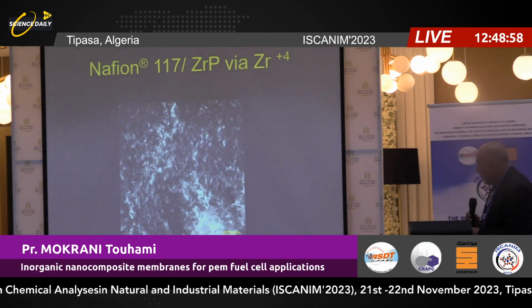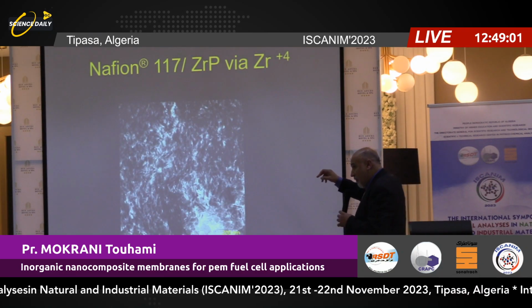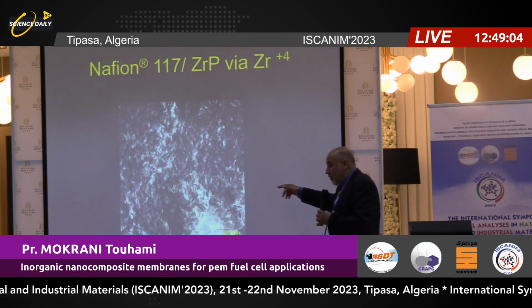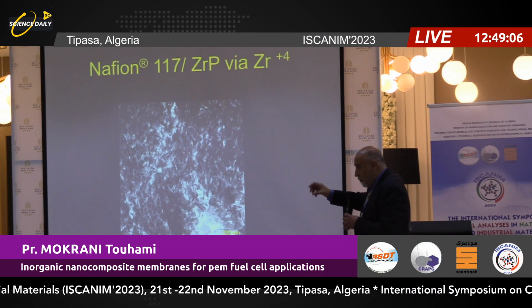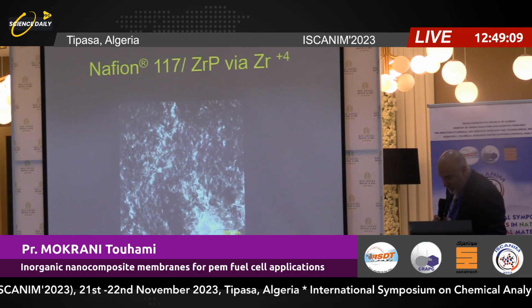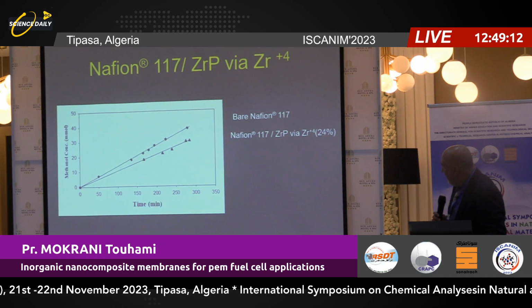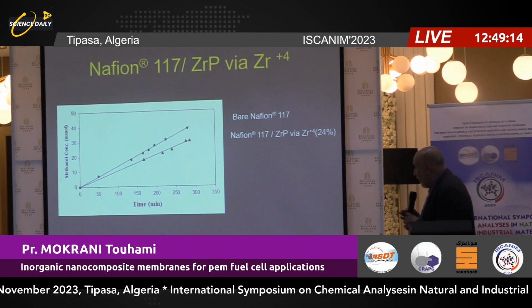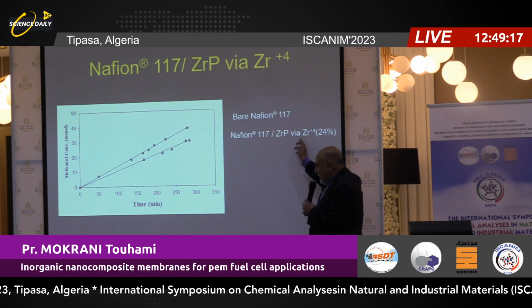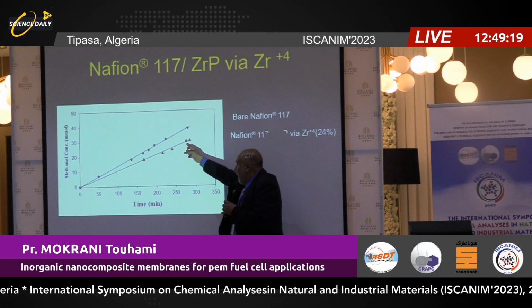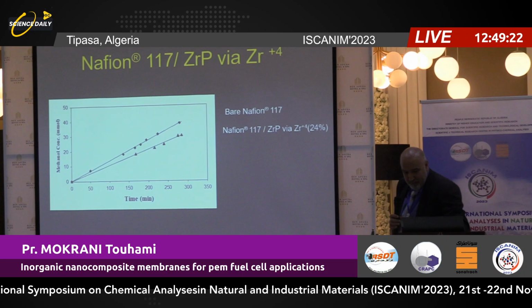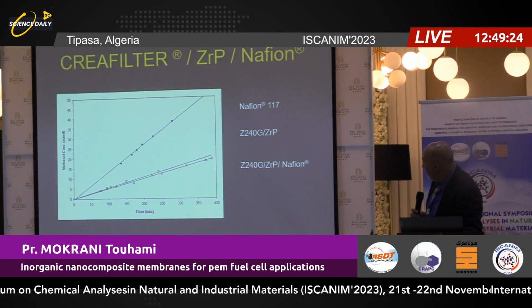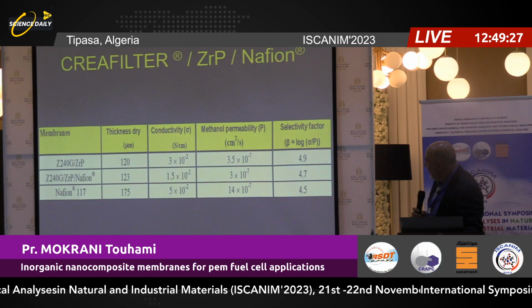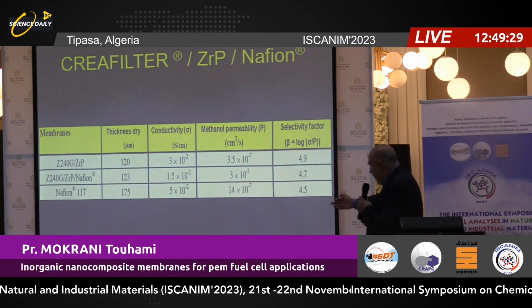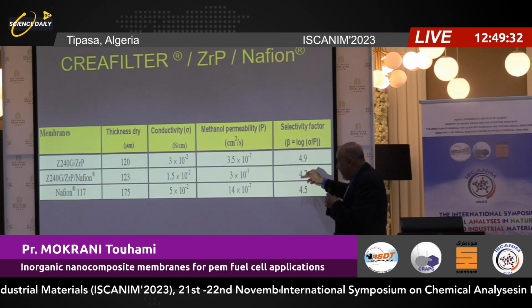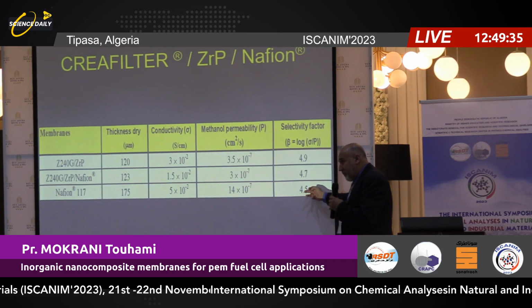Okay. So this one is also to confirm that with the ion exchange method, we still have nanomaterials, nanoparticles of zirconium phosphate. Here it's much better methanol permeability. So here we can see the reference 4,5. These two membranes are better than the reference.